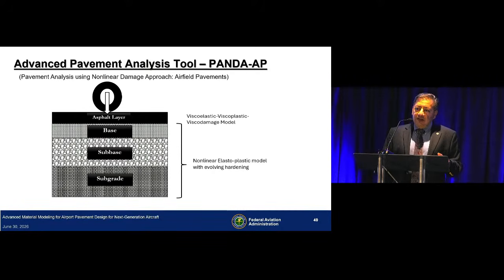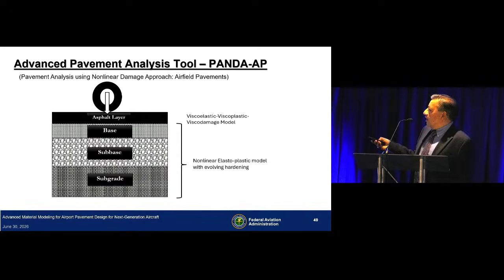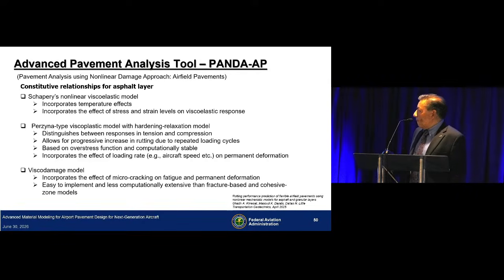But you also need to have a pavement analysis tool that can use these input properties. And that's something we are currently doing. We are working on developing this program called PANDA AP, which is pavement analysis using nonlinear damage approach for airfield pavements, where asphalt layer is modeled as viscoelastic, viscoplastic, and the aggregate materials and the subgrade is modeled as nonlinear elastoplastic materials with evolving hardening. So for asphalt materials, we use kind of a combination of Schapery's model to look at nonlinear viscoelastic behavior, and Perzyna type viscoplastic model to look at hardening and relaxation to account for permanent deformation in the asphalt material.